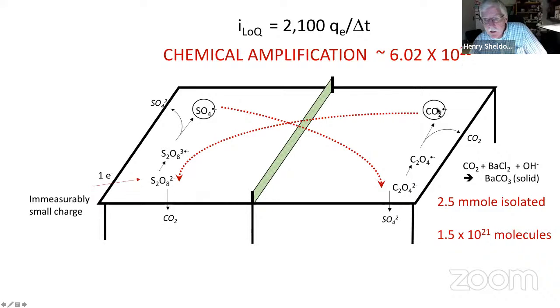Of course it's not, because you're going to lose some of these radicals by side reactions. But it must be really large, the amplification here, because we're getting out macroscopic quantities of CO2, and we can't measure this. The charge needed to carry that out is so small that we're unable to measure it at the current time. So the amplification must be really, really large.